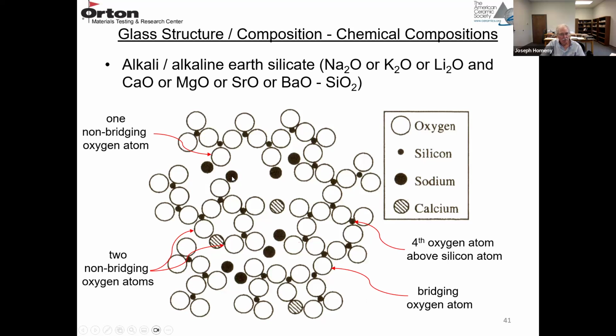So you can see that a sodium ion forms a non-bridging oxygen, and it's Na2O, so here's both of the Na atoms forming two non-bridging oxygens. But then a calcium 2+ ion forms two non-bridging oxygens. So here's one non-bridging, and here's another non-bridging. So one non-bridging oxygen atom per alkali ion, two non-bridging oxygen atoms per alkaline earth atom.